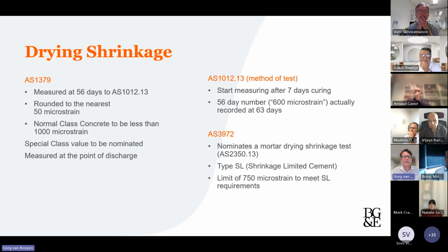And some key points are that the shrinkage we're measuring in the shrinkage test is after 7 days curing, and then it undergoes 56 days of drying. So it's a 63-day-old sample. Again, trying to improve shrinkage through selection of a type SL cement, there's a 750 microstrain limit for that. So as you can see, typically in those standards and the methods, the allowance for shrinkage is actually quite high comparative to numbers you may see in a specification, of less than 600 being quite commonly specified to get a lower shrinkage or try and control cracking.